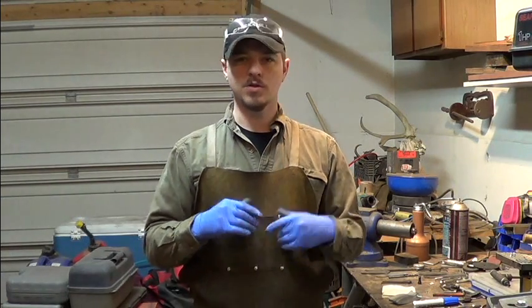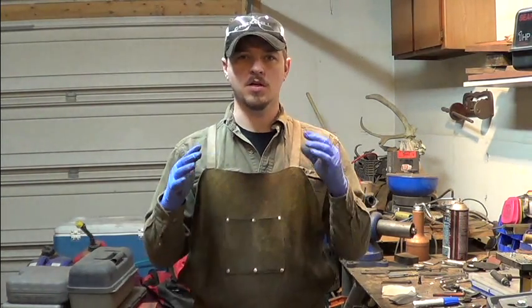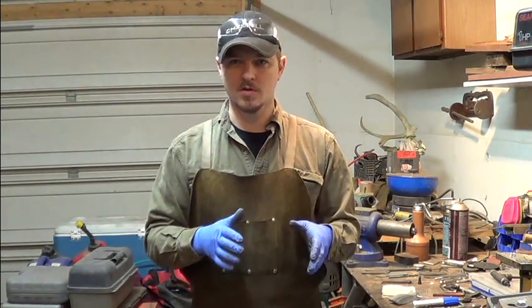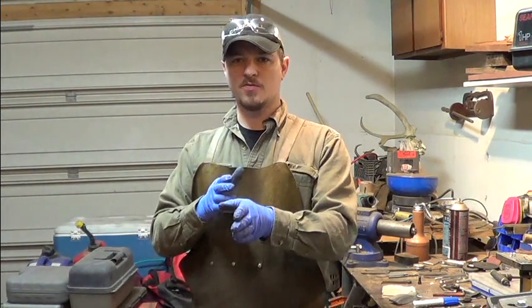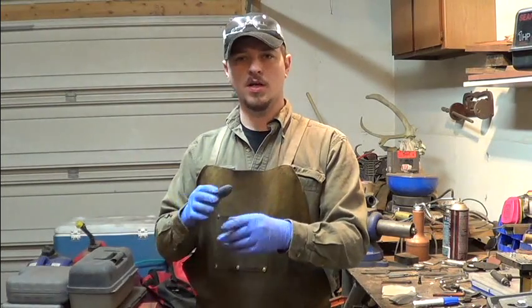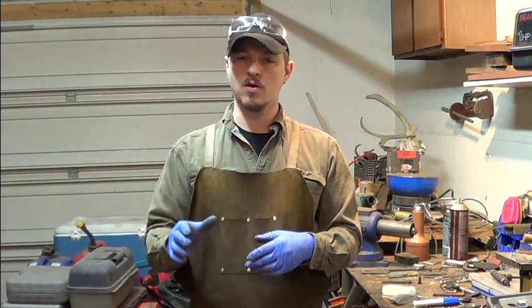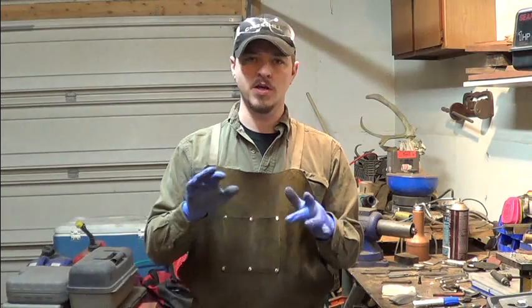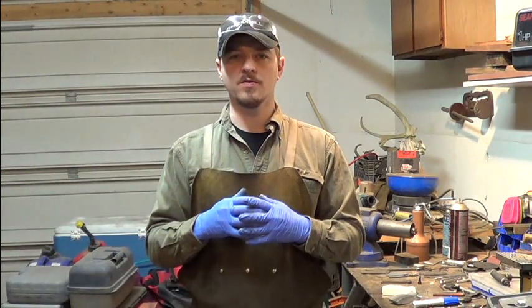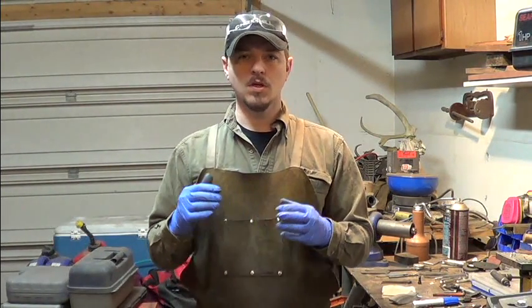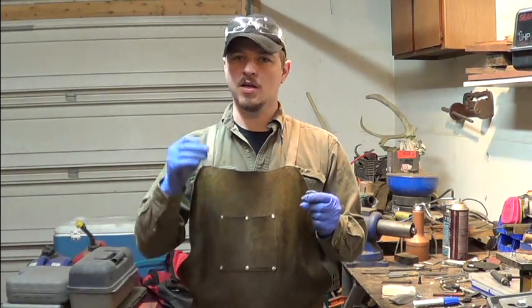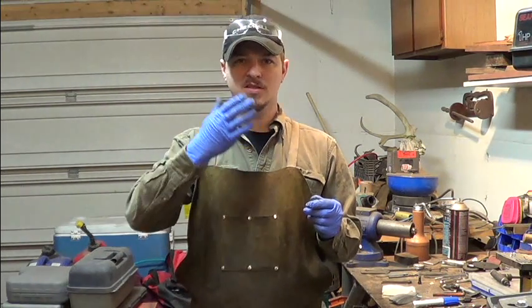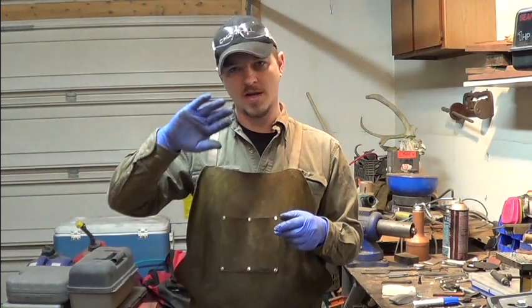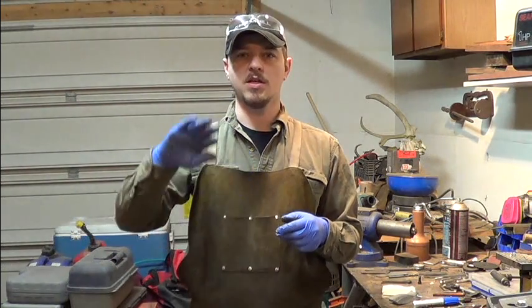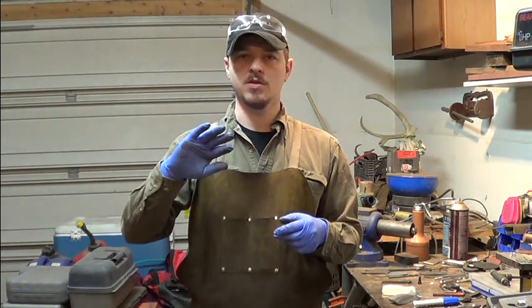And just to throw out what I do for heat treat, I start out, I grind at 60 grit, goes into the forge, gets hardened, goes in the oil bath, the whole 9 yards. Out of the oil bath, it's going to have that nice black coating that I showed you in one of the previous videos with Doug. That nice black coating, because all those 60 grit scratches, that black can be down in those 60 grit scratches. It's real easy to see when you get all those 60 grit scratches out with the 240.